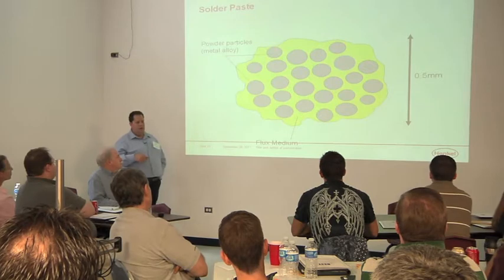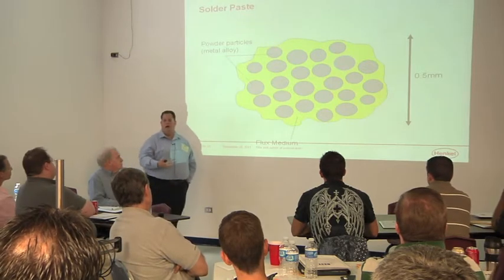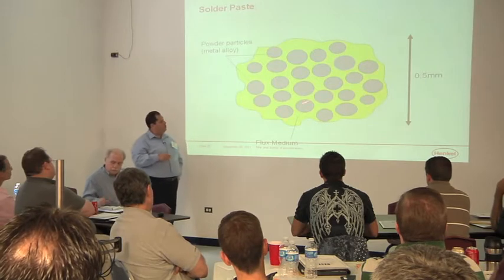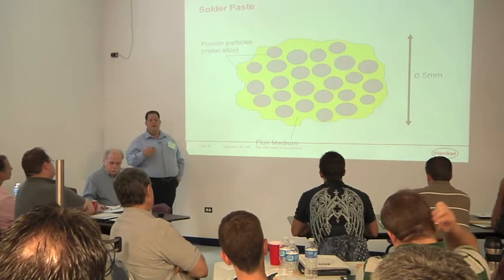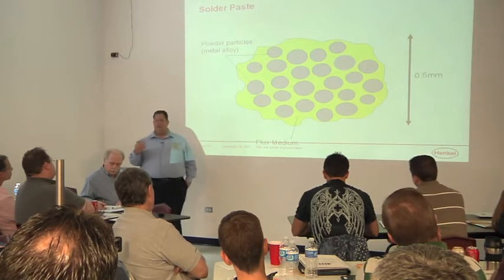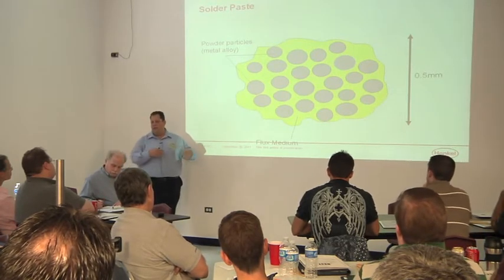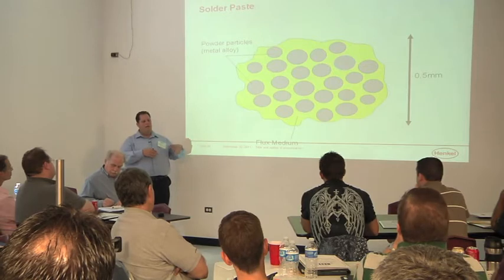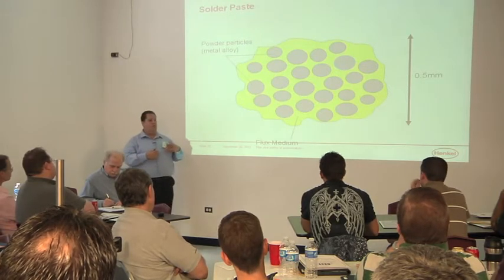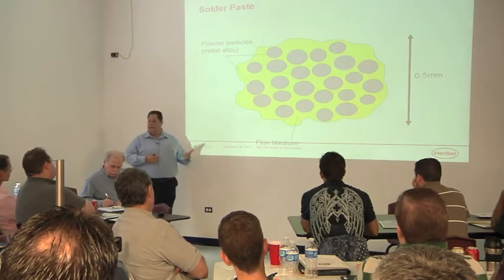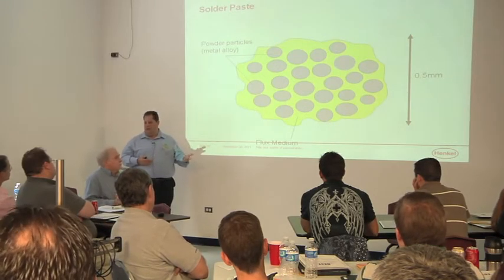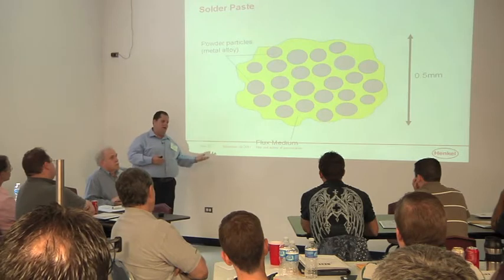Now this medium - I talked about formulating, about rheology and viscosity. There's stuff that we add to that medium, chemicals and things that give it those properties - what we call a gel structure or thixotropic agents. There are things we put in the medium that give it those properties, as well as all the stuff to remove oxides when you do soldering, as well as resist moisture uptake, because it would naturally do that.